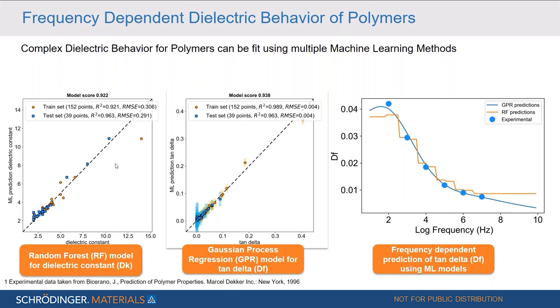On the left-hand side, we see the results for the prediction of the dielectric constant using a random forest model. And we see again here we have a very good agreement between the observed and the predicted dielectric constant. We can also predict the dissipation factor, tan delta, which we can see here in the middle. Here, a Gaussian process regression model was used. We see again here that we have very good agreement for both training and test set between the observed and the predicted values.